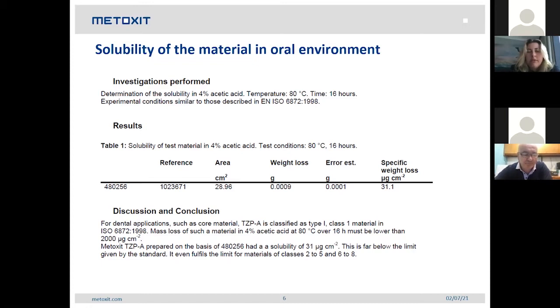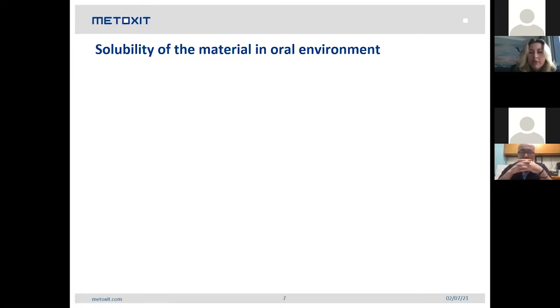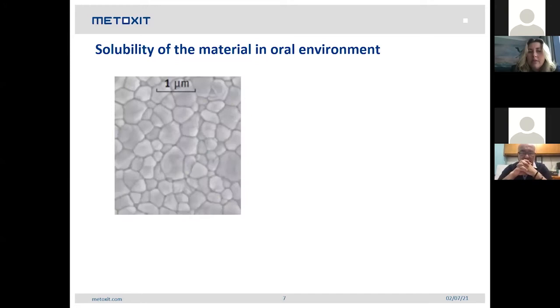So you see an excerpt of our test. Here you can see the specific solubility, and it's really, really low. It's only 31 micrograms, and it's very far below the limit given by the ISO standard. So this makes you sure that your structure is stable, even in an oral environment, which is the acid in your patient's mouth.